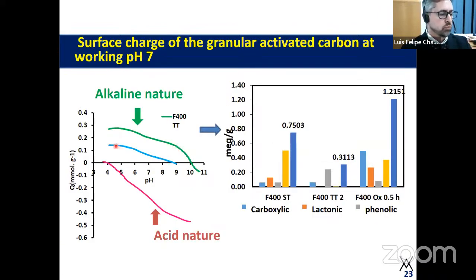The pristine electrode, which is the blue color profile, shows an alkaline character, as you can see. And this material was subjected to a thermal treatment to increase its alkaline character, its degree of reduction and its positive surface charge, which contributes to favorable electrostatic attraction of the arsenate or arsenic anion. And as a control, this material was subjected to an acid treatment that increased its degree of oxidation, of course, its acid character, and this in turn causes a greater density of negative surface charge, which contributes to an electrostatic repulsion of the arsenate.